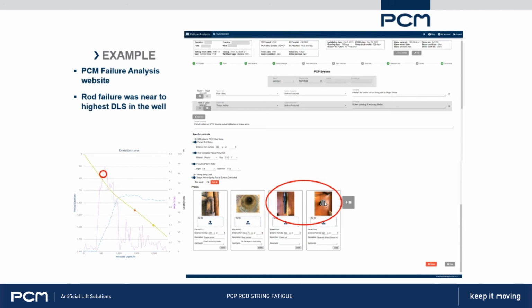This particular fatigue failure here, I added in this graph from our PCM design software because we had the analysis for this well in there. And I've marked where the failure occurred, which is very close to the highest dog leg in the well. A little bit above it though, and you'll often see that because the tension in the well is higher closer to surface. So you'll often see the failures being a little bit closer to surface than where the highest dog legs are. Or if you see two dog legs where maybe there's a higher dog leg deep in the well, it'll be the shallower dog leg, even though it's not quite as severe. That's where the failure will often be because of that higher tension.